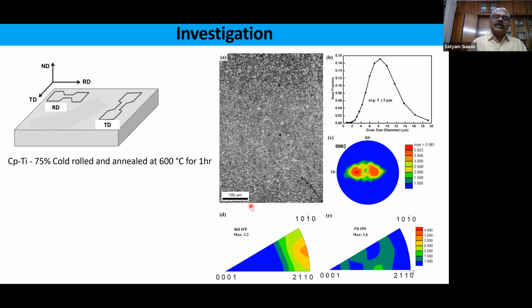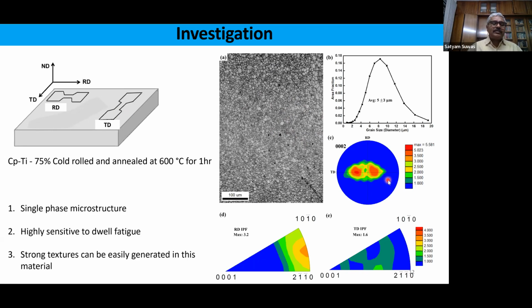First of all, the anisotropic aspect. So we took a plate of CP titanium, which was obtained by cold rolling and annealing, and nice equiaxed, very fine grains were there. Grain size was about 5 to 8 micron in most of the cases, and it has a split basal texture, which is very common in titanium. TD split texture is common in titanium or any hexagonal materials with a c/a ratio, or axial ratio, less than critical. So this was observed, and then this material was taken further for further studies, right? Because this combination, according to us, would lead to high sensitivity for dwell fatigue.